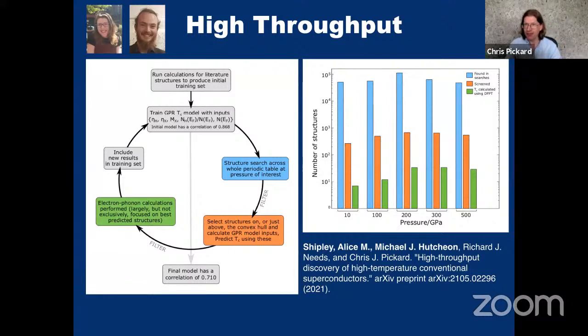We decided to go down this route because we have observed that in the case of the lanthanum hydride, that's indeed the case. So the cubic LaH10 is not actually the most stable arrangement of those atoms. It's actually a metastable phase. So considering metastability actually seemed to be quite wise. And in fact, we found as the result of our high throughput sweep that many of the best structures we found are actually the metastable phases. So it's highlighting the importance of metastability.